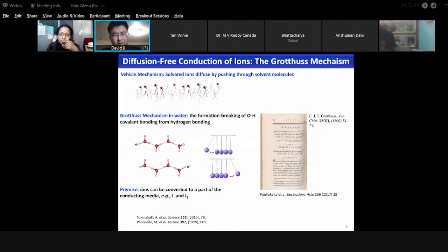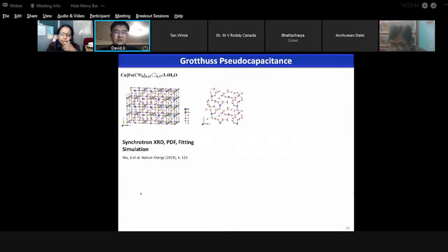All right, this is not just unique for protons. It could be other media, iodine, lithium in solid state electrolyte. You can also have those phenomena. But for water and proton, it is the most obvious choice for us back then. So we need to have water to have the Grotthuss mechanism. So then we tried to install a network of water molecules inside the solid of the electrode. And what we used is very obvious, actually, back then: Prussian blue, because we studied Prussian blue for a long time. And we just had to make Prussian blue defective.